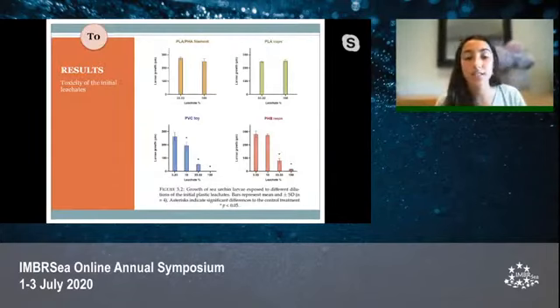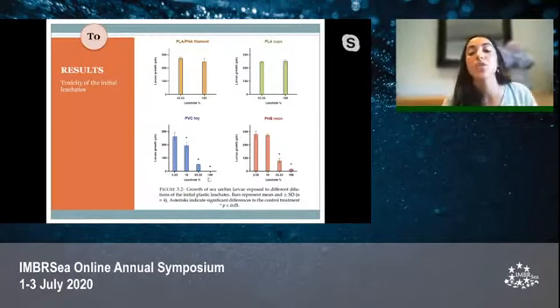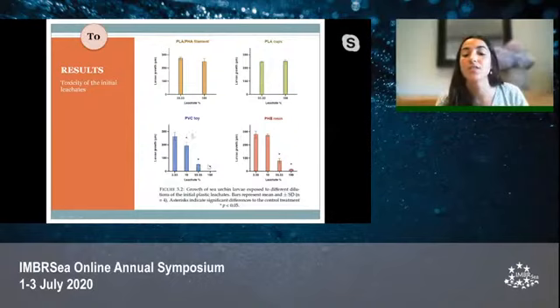So for the initial liquid, in this figure, I show you the larval growth in the y-axis, and in the x-axis, you have the different dilutions from most diluted to most concentrated. So for PLA PHA filament and for PLA caps, you can see that there were no significant differences with the control. Whereas for PVC toy and PHB resin, these asterisks represent that larvae exposed to these dilutions grew significantly less than the control.